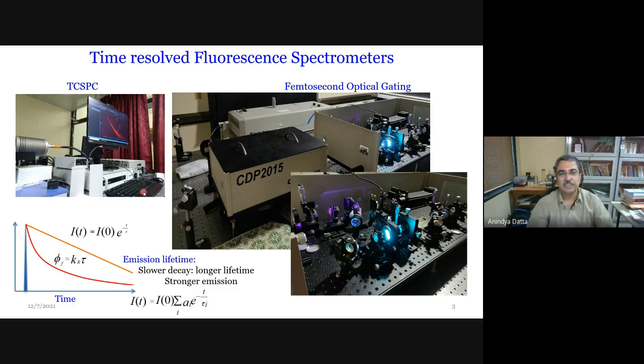Both these instruments are actually there in your institute, but just to make sure that everybody is on the same page, the crux of the matter in both the cases is we excite whatever it is that we want to look at by using pulsed light. So the light is on for a very small time, typically 100 or 200 femtosecond, and then it goes off. So what this pulse does is that it creates an excited state population all of a sudden. And then when the light is gone, this excited state population is left to decay on its own.